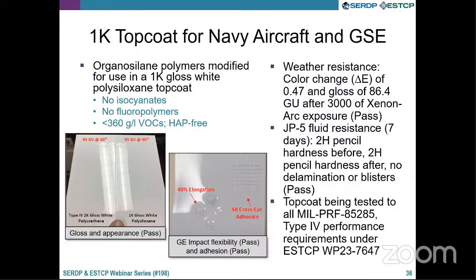You can see here with these top coats, we can produce gloss that is identical to type 4 polyurethanes. The top coats can demonstrate 40% elongation and very good adhesion. I have some other data here showing that even after 3,000 hours, we can have a color change of less than 0.5.